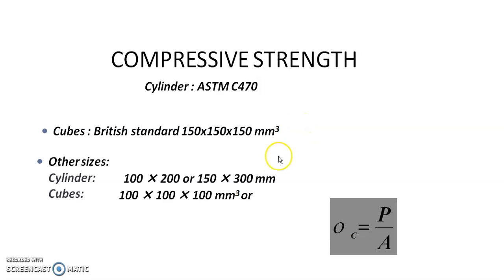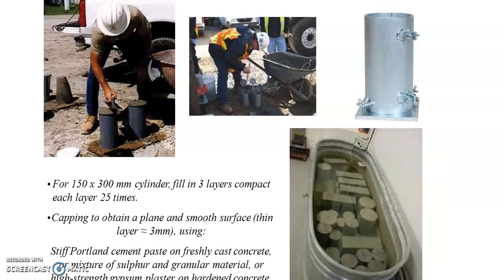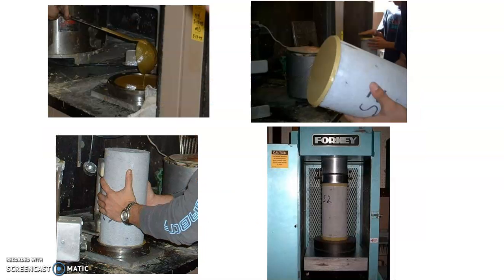This is the size of the cube normally adopted in the lab. The formula for finding the compressive strength is load divided by area — P is the load and A is the area — and the unit is Newton per mm². For making the cube, the inner side of the mold is oiled so that it will be easy to remove. This 150 mm cube is filled in 3 layers and each layer is compacted with a tamping rod of 25 blows. For the cube, no capping material is required. In case of a cylinder, the size is 150 × 300 mm. Filling is done in 3 layers and each layer is given 25 blows by the tamping rod. This cylinder needs capping at the top.